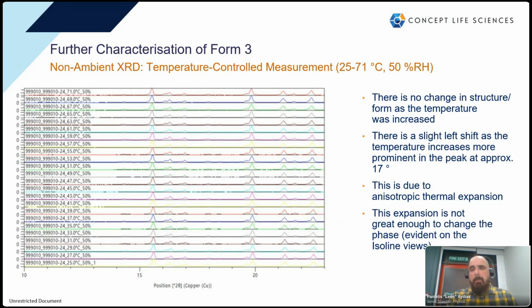That was close to the relative humidity on that day. There is no important change in the structure, in the form, with the increasing temperature. There is a slight left shift at the peak approximately at 70. It's more prominent there at approximately 17 degrees. This can be attributed probably to thermal expansion of the cell, and it is not great enough to change the